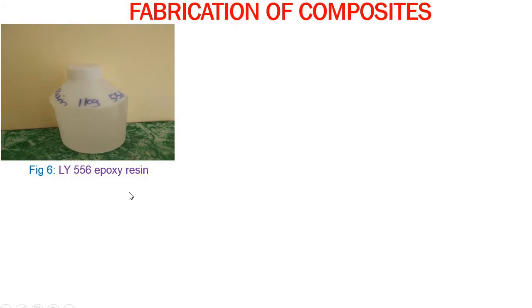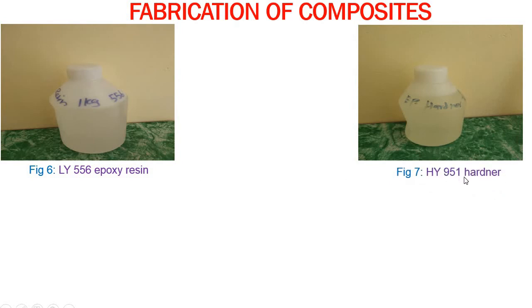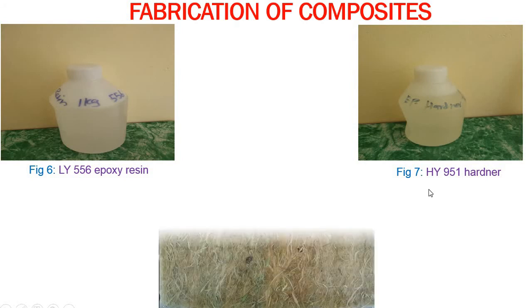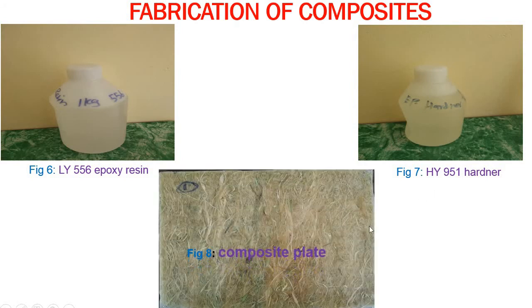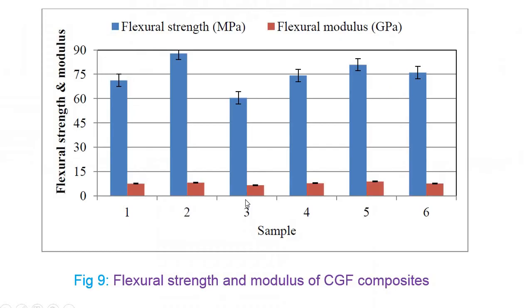I already told you we are going to use LY556 epoxy resin and HY951 hardener. The main reason is that the epoxy resin is of medium viscosity and also solvent free, and the hardener will give higher rigidity. We are going to use nearly a 50:50 ratio. Finally, using a compression molding machine, we will apply the load and pour the mixture of resin and hardener. Finally we will get the composite plate. You can see in figure 8 that this is the composite plate.